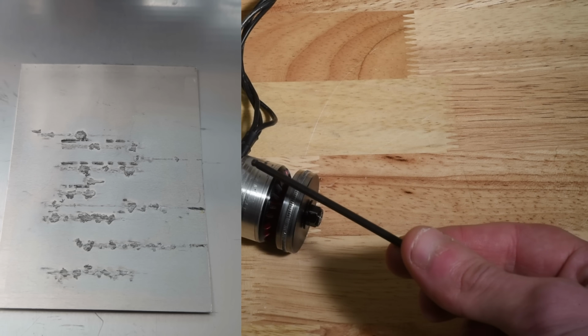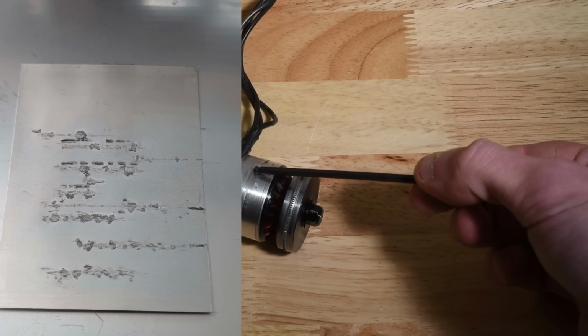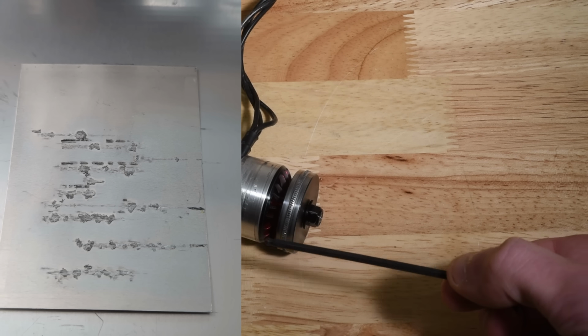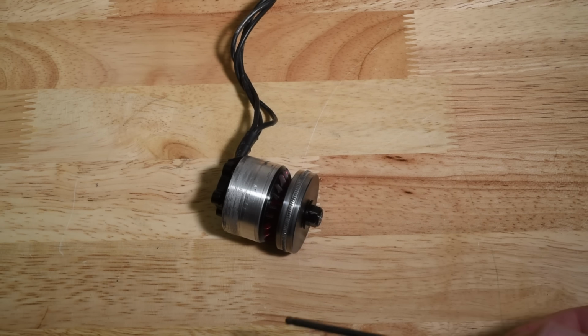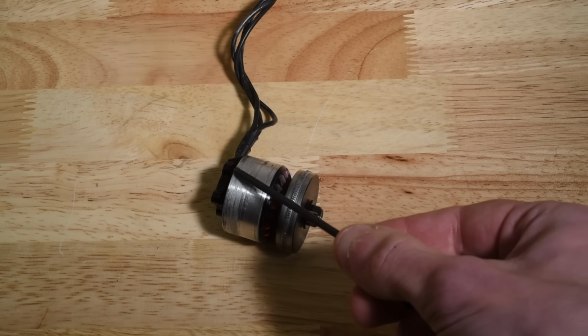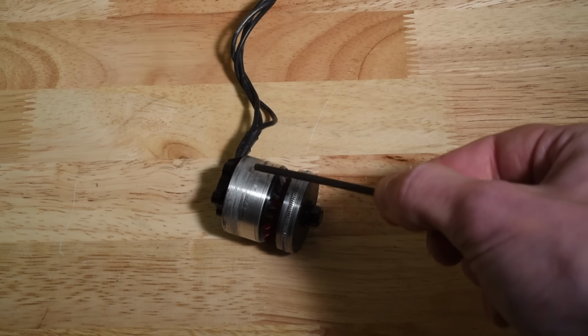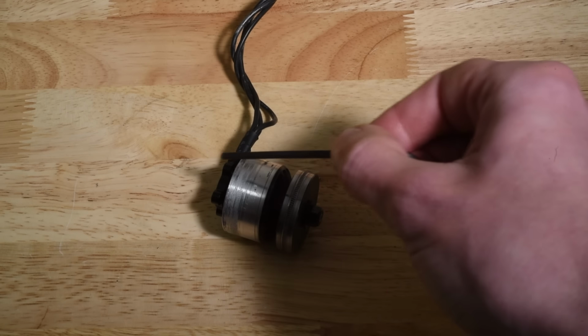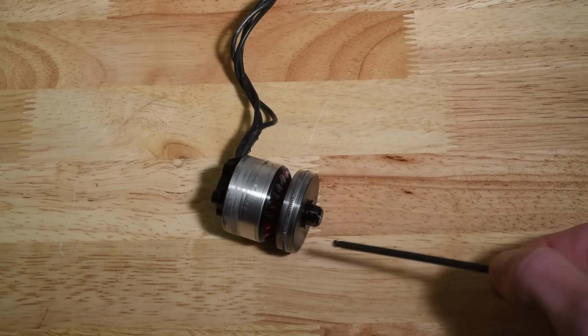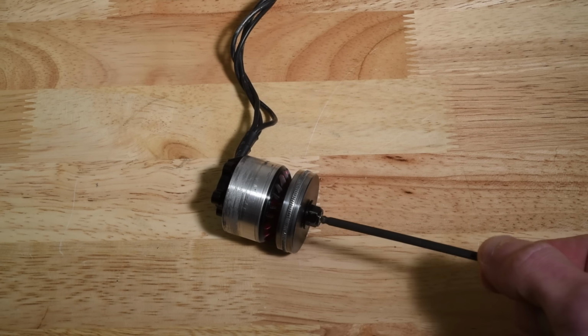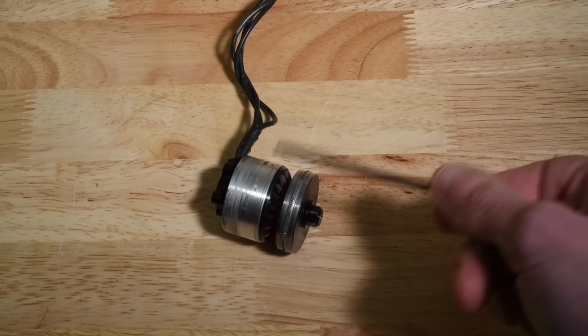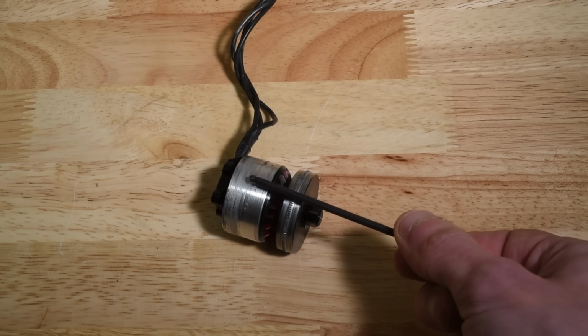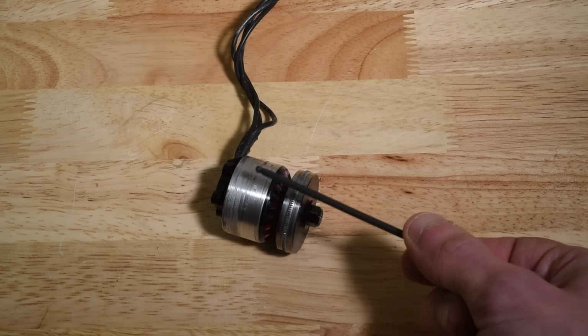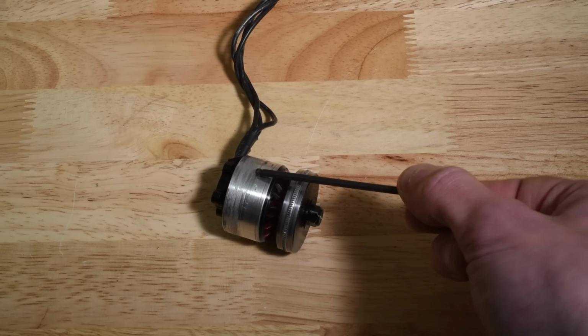Unfortunately, it also caused the magnets on the motor to get too hot and to lose a lot of their strength, so the motor's torque would decrease, and this would cause the motor to slow down and ultimately stall, especially since the bell is so wide, and that causes a ton of extra material to be spread out along the entire surface of the wheel, and that increases the torque requirement of keeping the metal flowing. Plus, since it's made of aluminum, it wears down quickly and its surface is always changing shape. So we did the next logical thing.